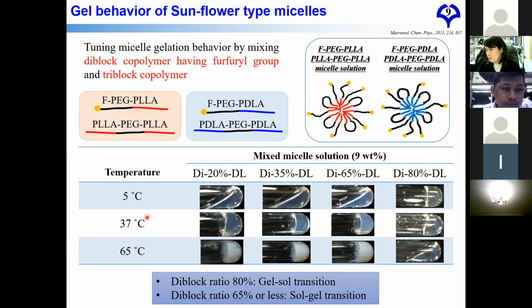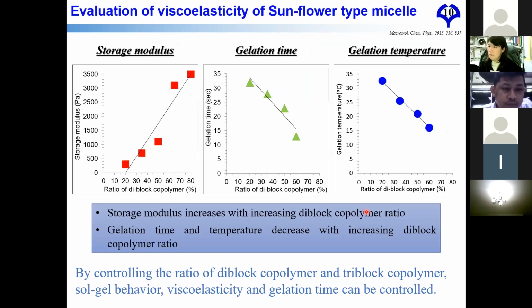And also, in this figure you can see that if the diblock copolymer ratio is too high, the sunflower type micelle will become a hydrogel at a low temperature. So when the diblock copolymer ratio is over 80, it is very difficult to apply for an injectable hydrogel. Also, in this slide we can control the storage modulus, the gelation times and the gelation temperature with the ratio of the diblock and triblock copolymers.